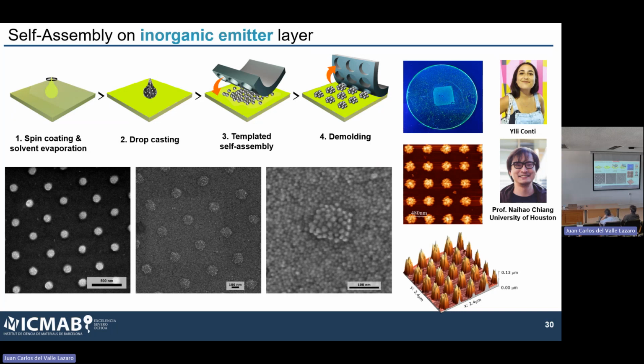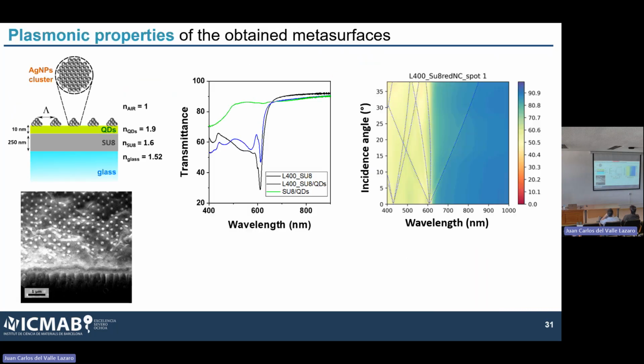So as you can see here, this is the morphological characterization. This is how the sample looks like. This is just an AFM to see a little bit the structure. And these are SEM characterizations where you can distinguish the silver particles from the quantum dots that are underneath. We also tried to do a cross section. Of course, we believe there are 1 or 2 layers of quantum dots. We're not able to resolve it with the SEM. But again, our SU8 layer, our thin film to create the waveguided modes, is there, and that is something that we can clearly see here.